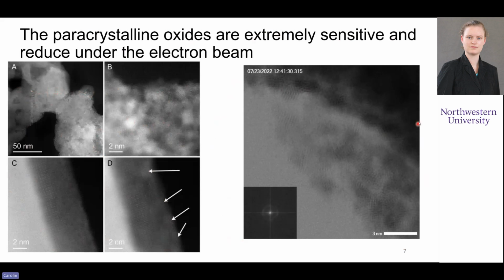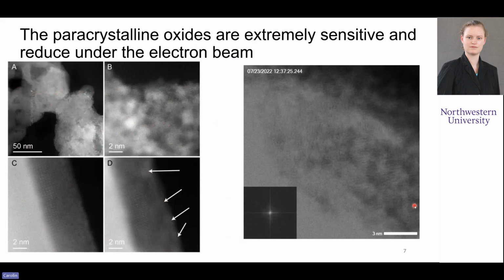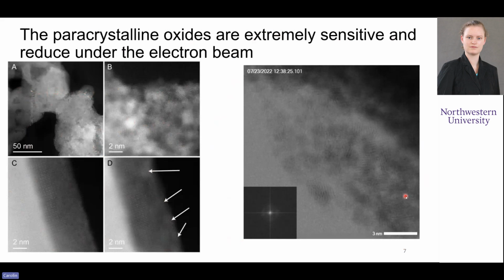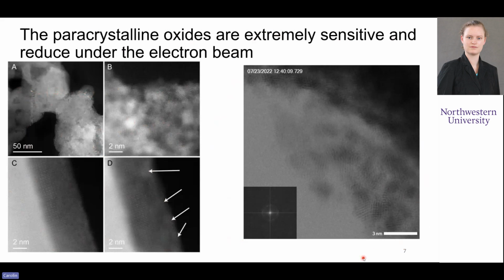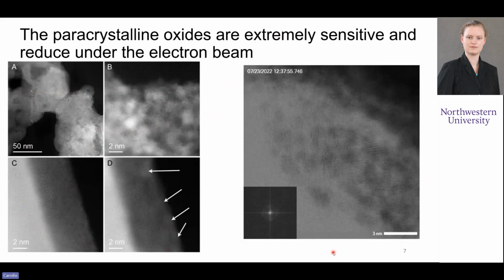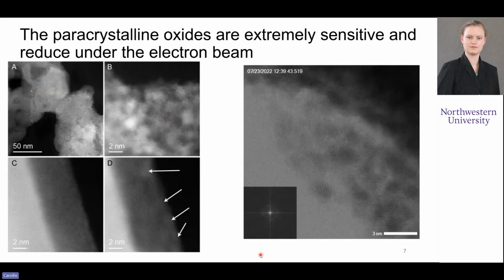And so you can see, if you look to the right over here, you see this kind of blurred region at the edge of the frame. That's the Axon drift correction, making sure this frame stays in place, because you can see this is drifting actually quite a bit. And you can see none of that in the final video because it corrects this out, even though the entire material transforms as it's moving. And so this is, even though we're not doing in situ experiments per se, this lets us work with these exceedingly sensitive materials and lets us capture the precise dynamics that go on in a material like this.